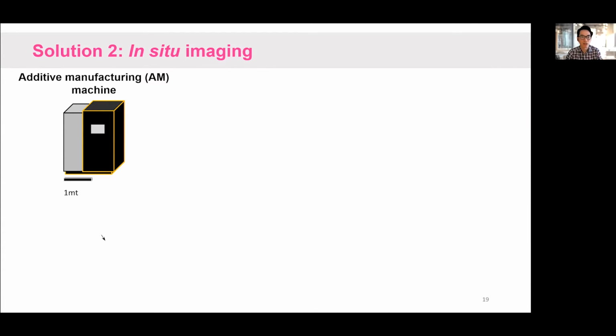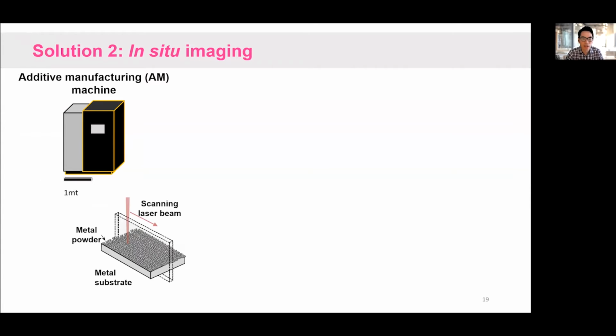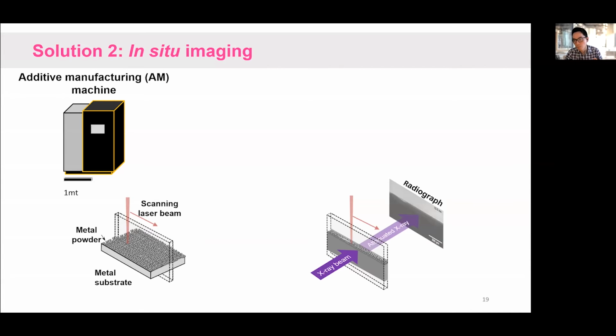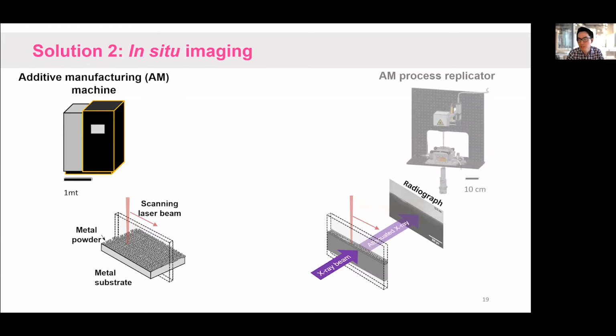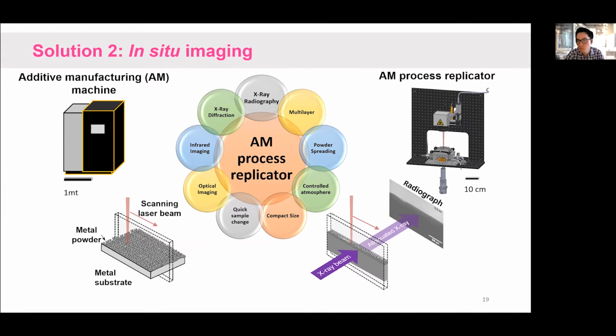So imagine an AM machine, and we have a powder bed within it, and we scan the powder bed. But during this process, we continuously use X-ray to probe the process and collect a series of images. And we call this a process replicator. We could actually do lots of things which involve engineering, because we needed to remote control this, which allows us to do powder spreading, control atmosphere, and so forth. And we wanted to use the process replicator to help us to better understand that.